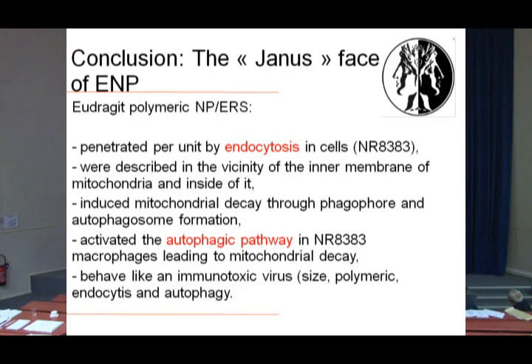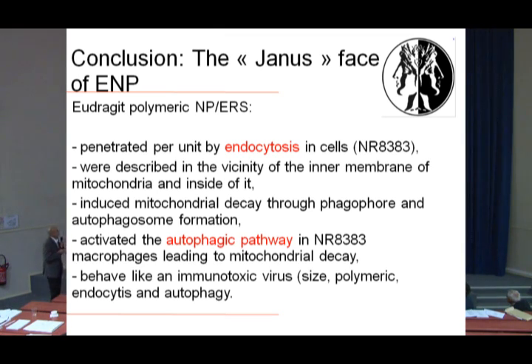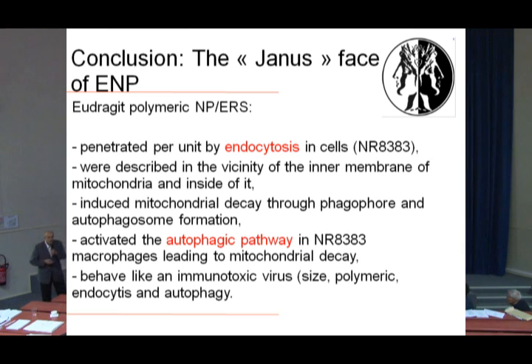In conclusion, there is a Janus face of nanoparticles. In certain cases, nanoparticles penetrate per unit by endocytosis, were found in the vicinity of the inner mitochondrial membrane and inside it, induced mitochondrial decay through phagophore and autophagosome formation, and activated the autophagic pathway. They behave like an immunotoxic virus, with analogy in size and polymeric nature for endocytosis and autophagy.